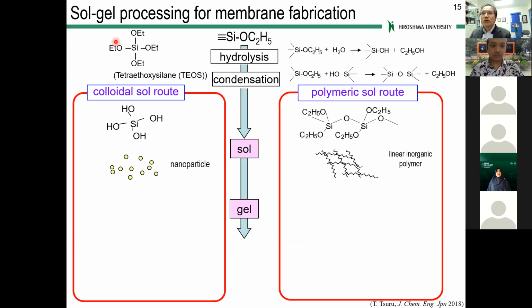Now, this slide shows typical sol-gel processing of membrane formation. A typical alkoxysilane precursor is TEOS, tetraethoxysilane, silicon with 4 ethoxide groups. This ethoxide group, OC2H5, is hydrolyzed with water to form silanol groups. These silanol groups further condense to form siloxane bonding so that we can make a network or particles. Depending on preparation conditions, it is possible to make a colloidal sol, like nanoparticles, or a polymeric sol, which gives us linear-like inorganic polymers.